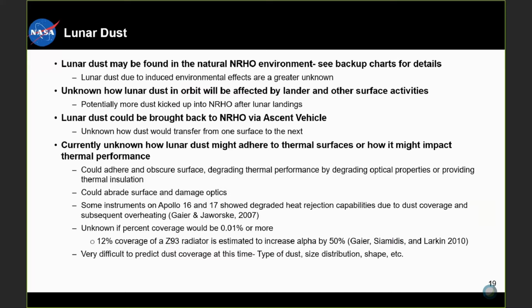So we don't know how lunar dust might adhere to thermal surfaces or how it might impact thermal performance. We have some past information on this. It could adhere and obscure the surface, which would degrade the thermal performance by degrading optical properties, or it could just be a dust layer on the surface and provide thermal insulation. It could also abrade the surface and damage optics that way. Some instruments on Apollo 16 and 17 showed degraded heat rejection capabilities due to dust coverage and subsequent overheating. So we have experienced this before on the surface. I think we had a couple of failures on battery radiator heat rejection.